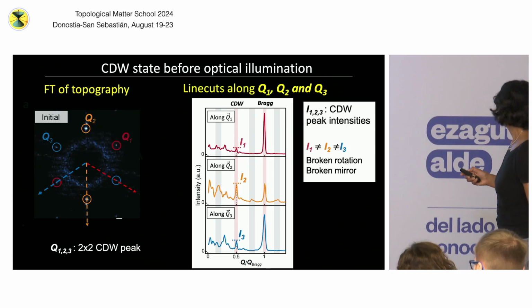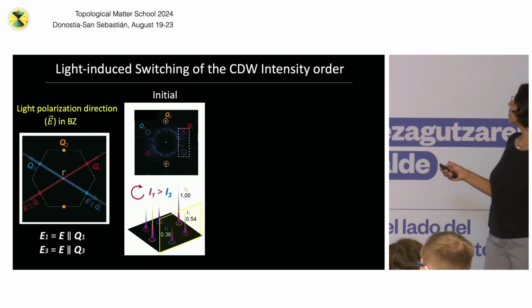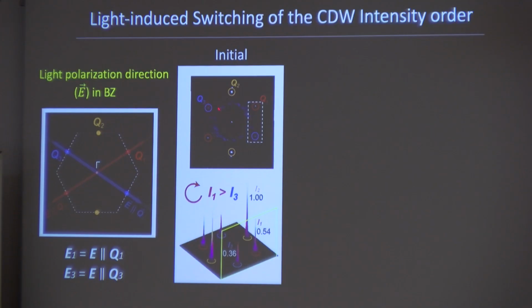Okay. So here's our experiment with the light. So let's just focus on these two charge density wave peaks. What we did was we can control the electric field of the light to point in any direction we wish. And we use that electric field, so we either point it in this direction or this direction. And by pointing the electric field of the light in different directions, you will see we are able to manipulate the intensity of the charge density wave, okay? So this is our starting point.